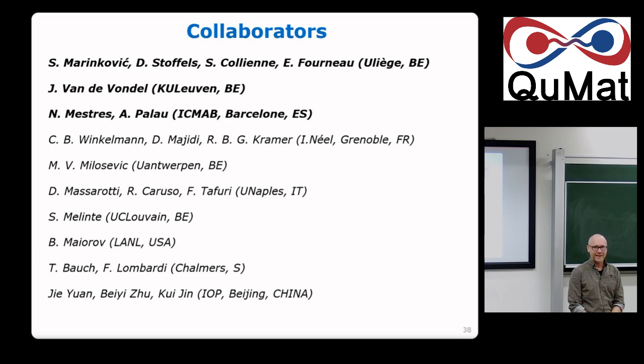That's something we wanted to try. We were talking today about having superconductor-ferromagnet-superconductor structures to have spin triplet currents, and for that you need gaps which are like 10, 20 nanometers. It's very difficult to target. So we wanted to electromigrate only one layer, not the other. It was one of the plans, but we found another way to try to do that, so we'll go for that one.